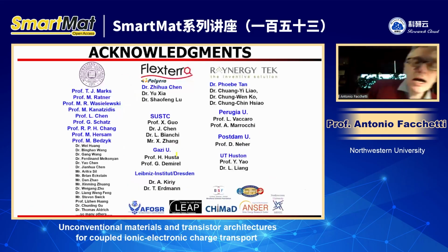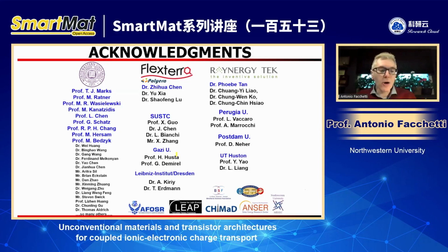Okay, so with this one, I conclude. I went a little fast. I apologize, but I hope I convinced you that porosity can be achieved in many different ways, with and without polystyrene. And by using a porous structure, you can get better ion penetration. The porous honeycomb structures are also elastic.